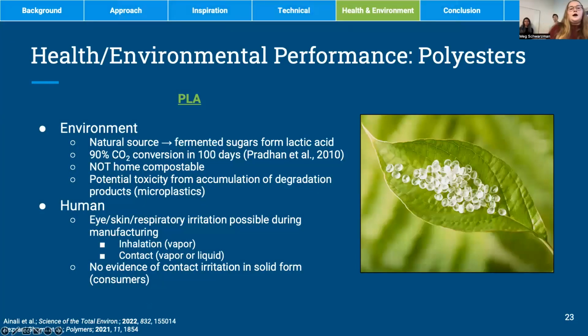Our polyester, as previously mentioned, is PLA, polylactic acid. So one of the major red flags here is that this is not home compostable. It is biodegradable with 90% carbon conversion in 100 days, which does meet that ASTM standard. However, it is not able to be composted at home. It's only able to be composted industrially. And that was something that was really important to Sway. So that was one of our major red flags here for this strategy.